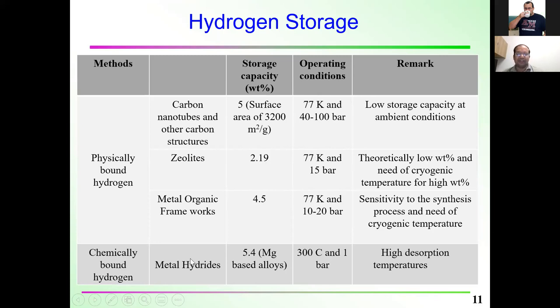If we attach hydrogen chemically, there are a lot of metal hydrides people are working on in this area. Its storage capacity is 5.4% if we use magnesium-based alloy. But look at the operating condition for charging and discharging hydrogen: it's 300 degrees Celsius at one bar pressure. Pressure is okay here, but temperature is still a bit high. We need to find some material that can store and release hydrogen at atmospheric conditions. That is my interest, my goal.